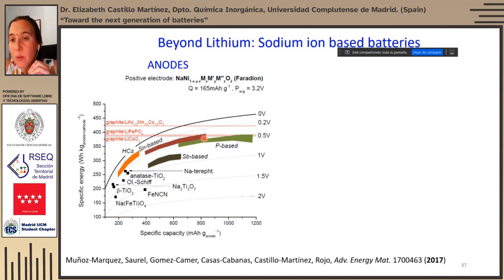but they have other advantages, such as you can use an aluminum current collector in both electrodes instead of having to use the copper current collector that is in the lithium anode, because sodium as well as potassium do not form alloys with aluminium, and therefore you don't need to use copper. And aluminium is lighter than copper. Tin-based anodes and phosphorus-based anodes do have very large capacities because they are mostly based on the alloying reaction, and therefore they do have the issues related to pulverization and large volume expansion of alloys material. And hard carbons are actually the alternative that is being used in the initial commercial sodium-ion battery.